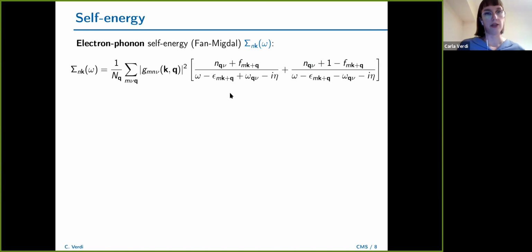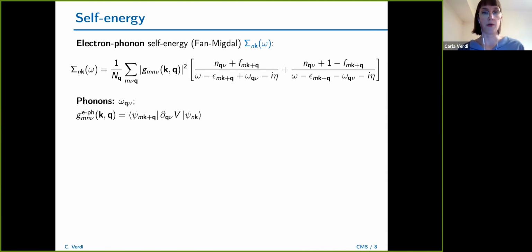So we have n is the electron index, k is the electron momentum. We have a summation over bands, summation over phonon modes and phonon momenta. g is the electron-phonon matrix element. n is the Bose-Einstein occupation factor. f is the Fermi-Dirac one. And then we have the electron energies and the phonon energies. So as I was saying, g is the matrix element. This is the trickiest part in this expression. It basically is given by the probability amplitude of an electron that is in an initial state nk to be scattered in a state mk+q by a phonon perturbation.